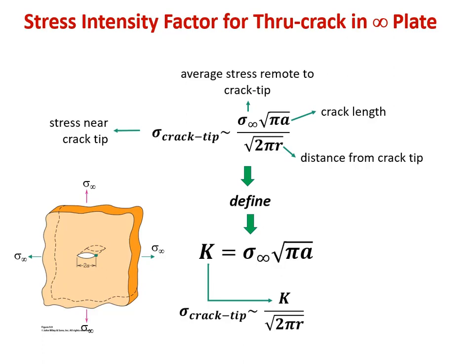This is effectively the same expression with a little bit different words. Rather than saying sigma yy, we're now saying sigma crack tip. So we're saying the stress at or near the crack tip is equal to the applied stress on the whole material, again, with our square root of pi times the crack length over square root of 2 pi times how far away we are, again, out ahead of that crack. If we take just the numerator of that expression and define it as its own constant, we're now defining something that's independent of location in the material and just calling out what we applied, which we could control, and some measure of how big the crack was to begin with.